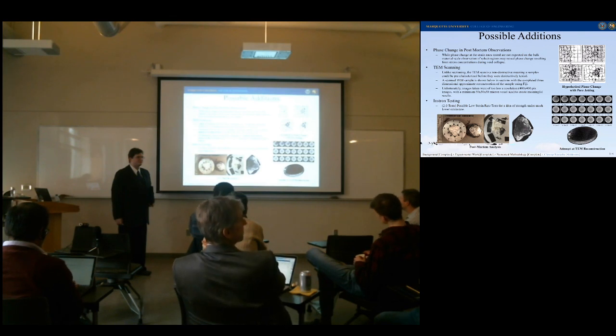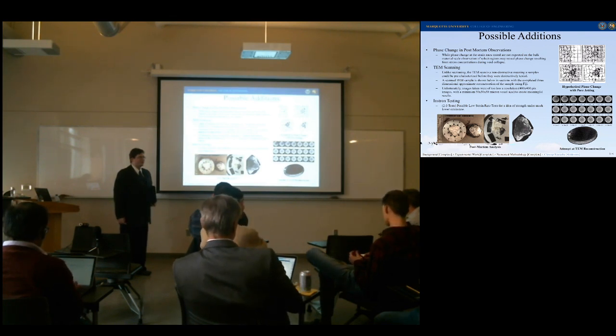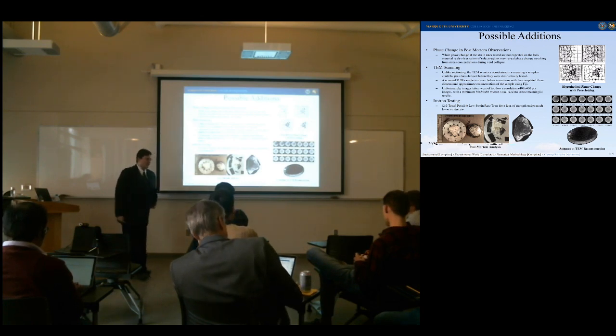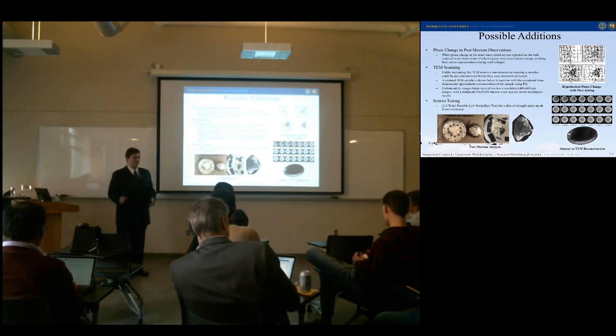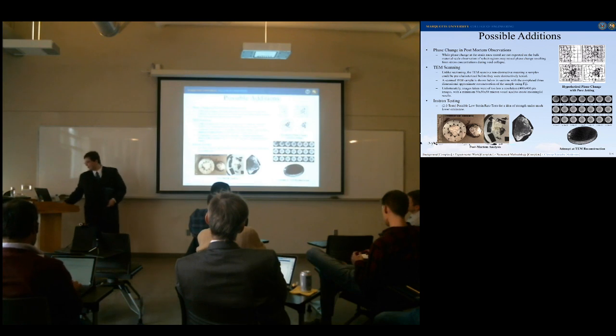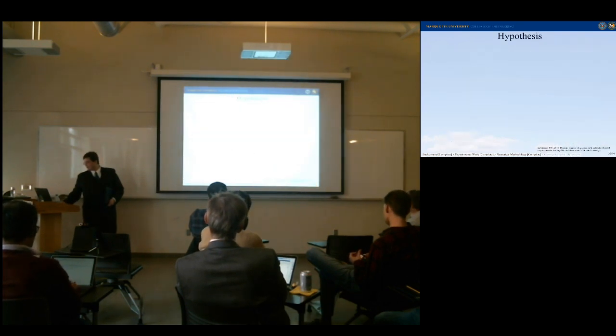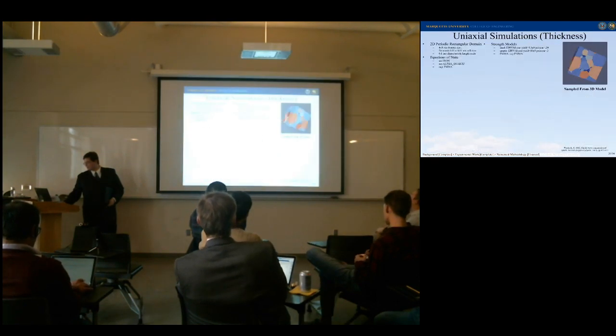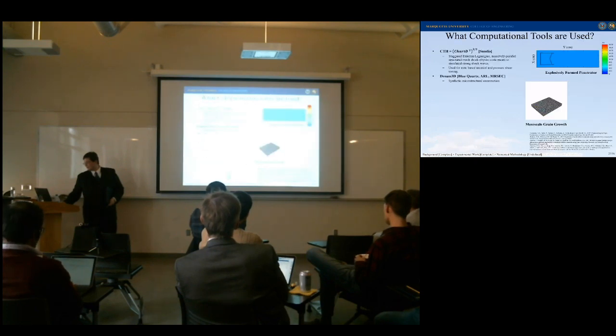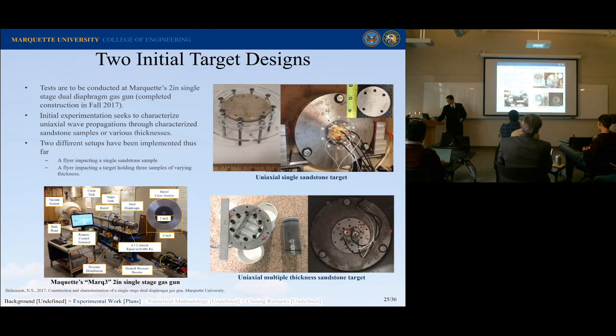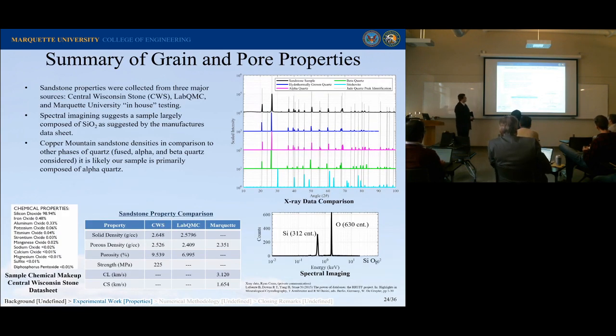So is this stuff primarily crystalline, or is it all amorphous? It looks like it's primarily crystalline based on the X-ray powder diffraction that I was doing before. The peaks that were there were indicative of crystalline behavior. Let me try and get back to that slide. So if you look at these different peaks right here, these are crystalline peaks. There is a slight hump over here, and that could be a little bit of amorphous silica, but the vast majority of the signals that I was getting were definitely crystalline peaks. And comparing with other crystalline materials, the one that it matched up best with was alpha quartz.